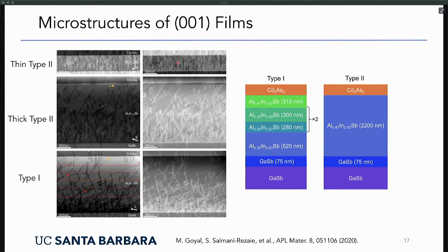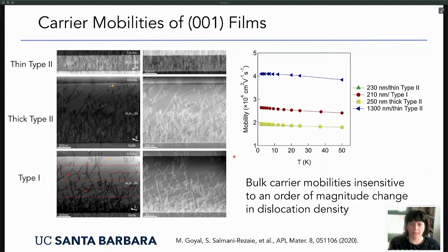So for example, here's a thin buffer layer, and there we have a high dislocation density in the cadmium arsenide. If you use thicker buffer layers where we have fewer dislocations in the buffer layers, we also get fewer dislocations in the cadmium arsenide. Okay, so these are the challenges if you work with mismatched substrates. In this case, the lattice parameter of gallium antimonide is quite different from the buffer layers, and so these are the very typical challenges with epitaxial growth on mismatched substrates, and we suffer from the problem of not having a lattice matched substrate.